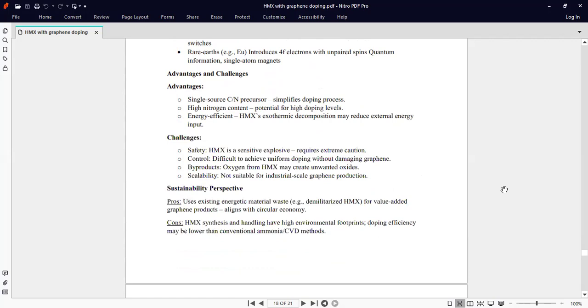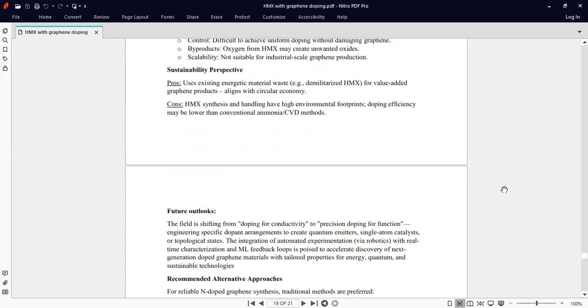The advantages and challenges of graphene doping. The advantages are a single source of carbon and nitrogen precursor, high nitrogen content, and it is also energy efficient because of the HMX exothermic reaction. The challenges are safety, because HMX is a carcinogenic material. Its control is not easy, because it is not easy to transport byproducts. Oxygen from HMX may create unwanted oxides, and so scalability is not suitable for industrial scale. The stability and sustainability challenges are using existing energetic materials and their synthesis and handling environmental footprints, and doping efficiency may be lower than conventional ammonia CVD methods.